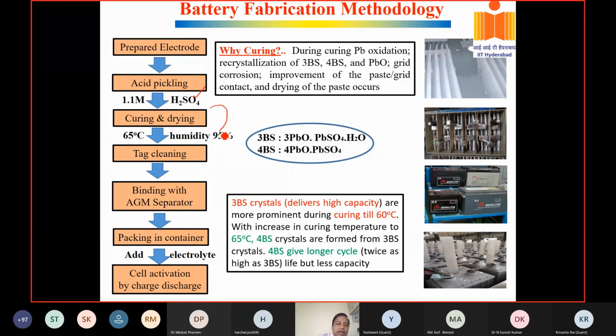This is the important stage of the battery. Very, very important stage, the curing and drying. It has to be done at a maximum of 65 degrees centigrade. If you go above 65, 70 degrees centigrade, your cell is not going to work at all. It will be very, very hard. So some people go below 60 and some people go around 65 to 70.